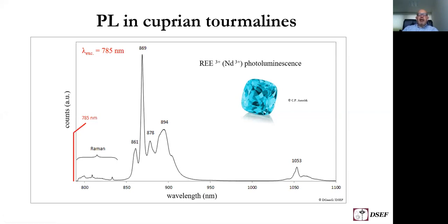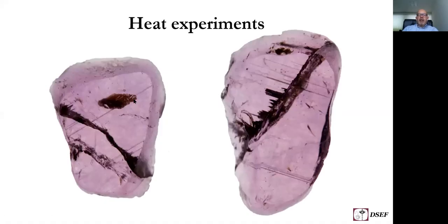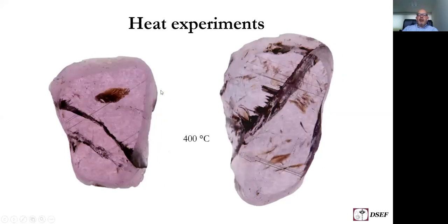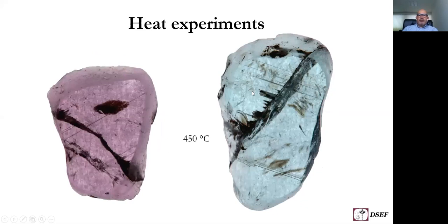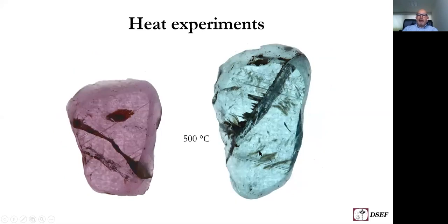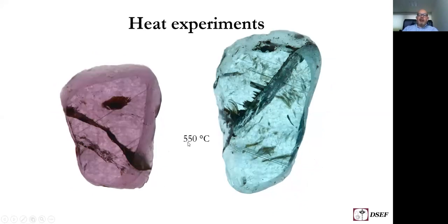So what we did is we heated stones. We took one, this is a sample that we just sliced into two pieces. The one on the left we kept as a reference, and this one we heated. At 400 degrees, you see already that the color is changing. 450, the stone is already blue. 500 degrees, sort of a greenish blue. And then at 550 degrees centigrade, we stopped, leaving behind this very attractive colored stone.